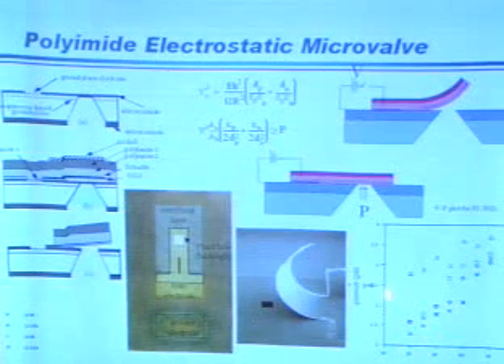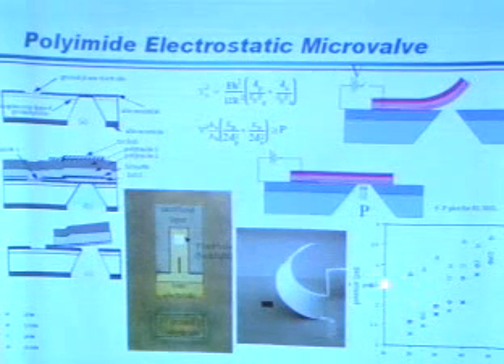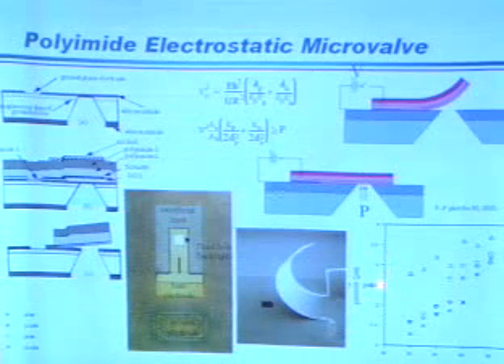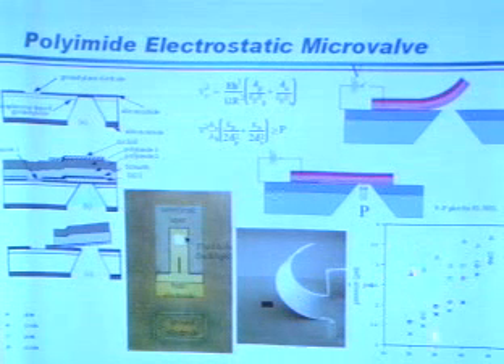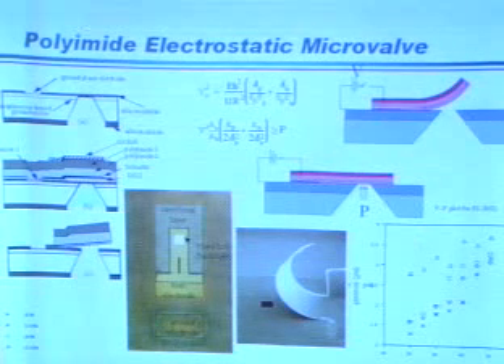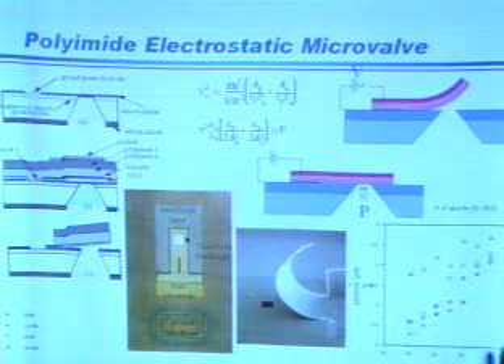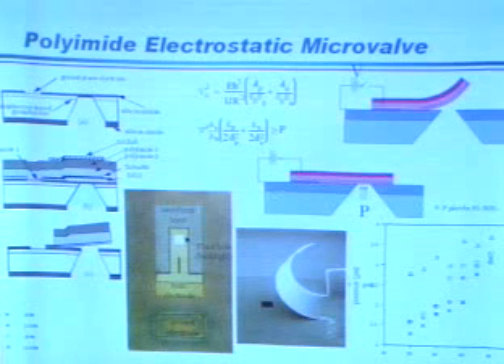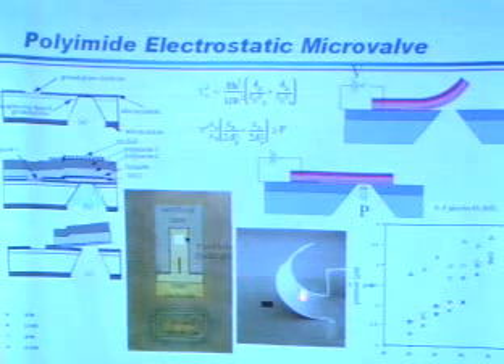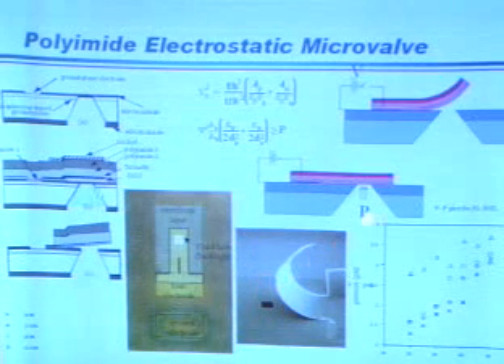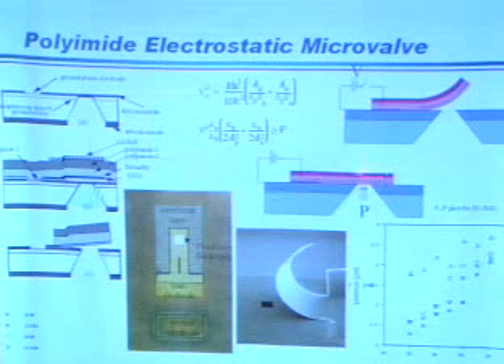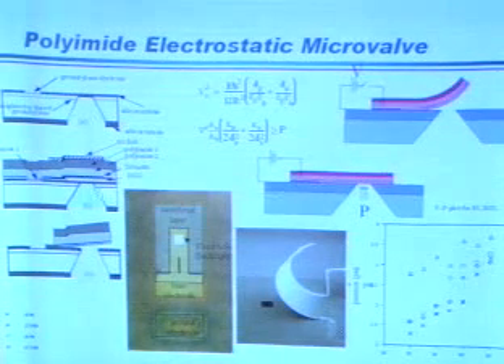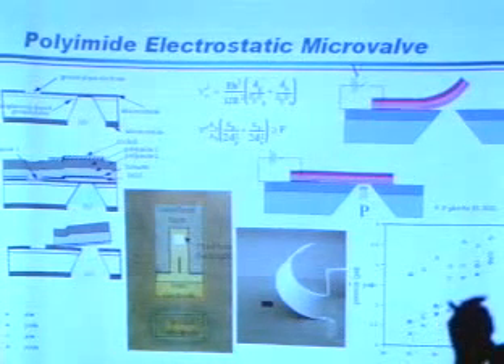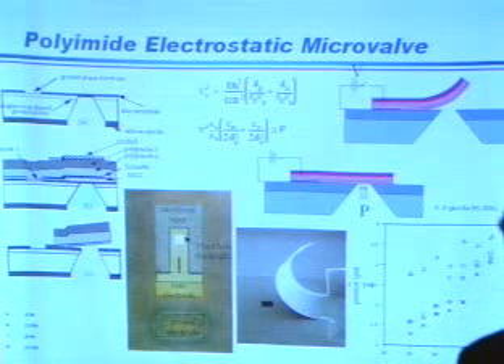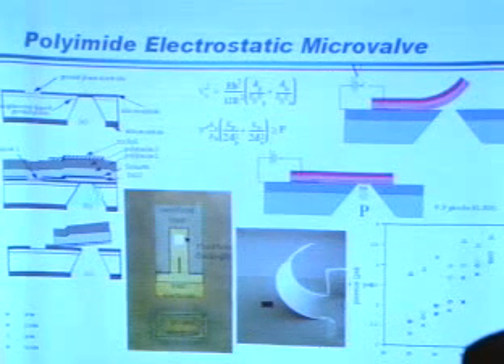And we were up to about, it's not very large forces, but about 3 to 5 psi at maximum, because we found that the flexibility actually was not a good thing when you have two materials that were adjacent to each other in terms of the softness. If you start deforming the membrane around the periphery here, then you allow an initial crack to generate, and much like fracture mechanics, it will just propagate that crack. So the hold-off pressure was not as much as we expected.